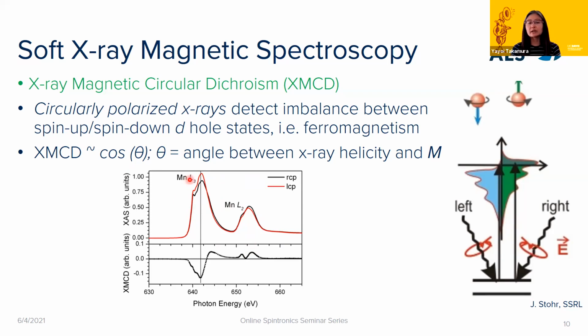And so for each material, you get a sort of fingerprint of which elements are magnetic in the material, and you can tell not only that it's manganese, right? We always know that the manganese absorption edge is around 640 electron volts, but the line shape of this particular spectrum tells you whether it's manganese 3+ ions, which are magnetic, or manganese 2+ ions. Similarly, both the XAS and the XMCD spectra give you that kind of fingerprint. So it's a pretty powerful technique.